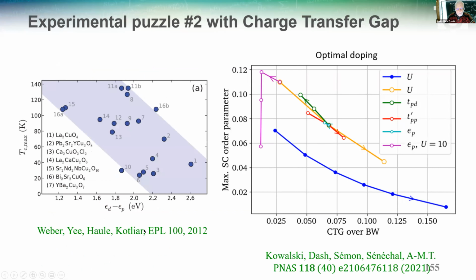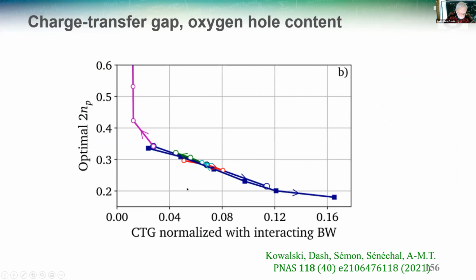This correlation was noted before in this paper, except that what was used were the bare parameters, epsilon P minus epsilon D. What I'm plotting is as a function of the observable charge transfer gap instead of the bare parameters. Now, are these two different ways of optimizing TC? Now I'm answering partly the question of Piers: this optimal hole content on the oxygen, the value of 2NP where the superconducting order parameter is largest, is inversely correlated with the charge transfer gap normalized by the interaction. And you see that both models now fall on top of each other.